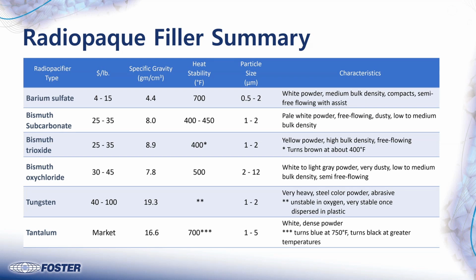What has changed in the years, the decades, of all of these radiopaque fillers? Particle size control. Some of these things are jet milled, so you can get them down to finer particle size, a little bit higher performance. Not that smaller is better, but in some instances you do want smaller particle size. But also the particle size distribution, the quality control on these ingredients has gotten better over time, and also the dispersion. So the quality has gotten better, but the chemistry has been the same for decades.